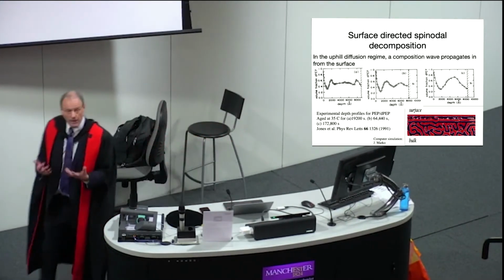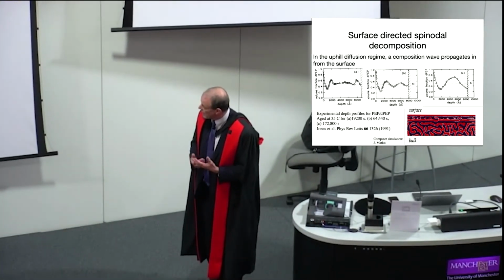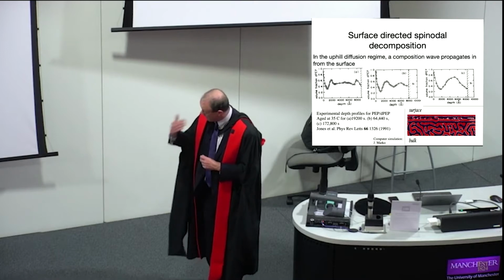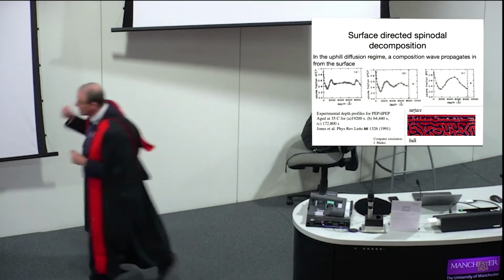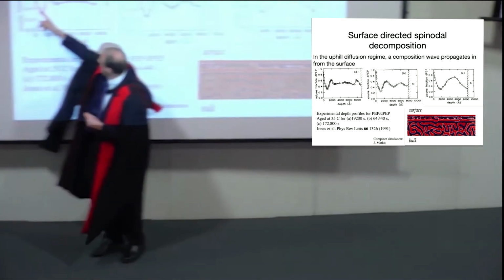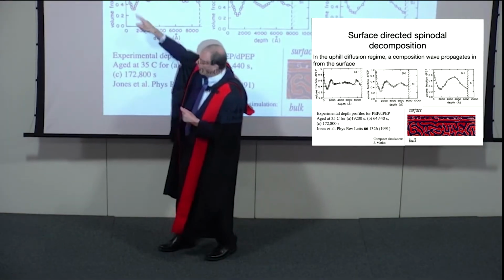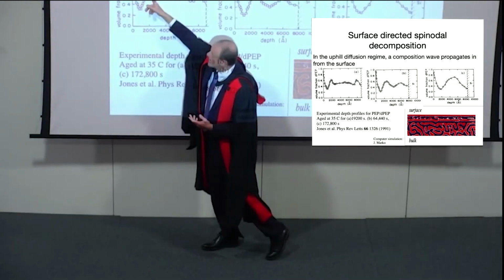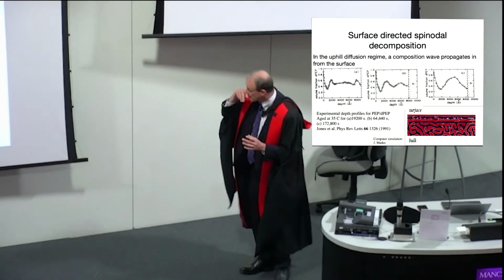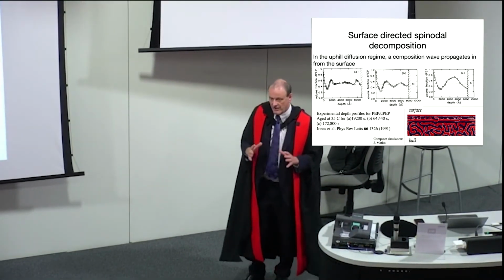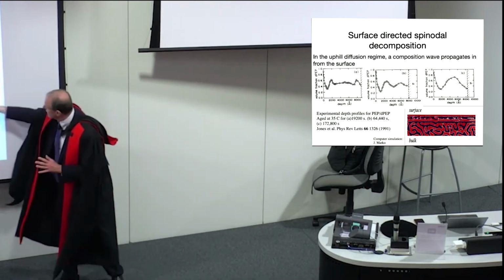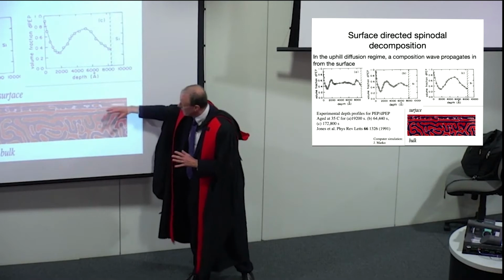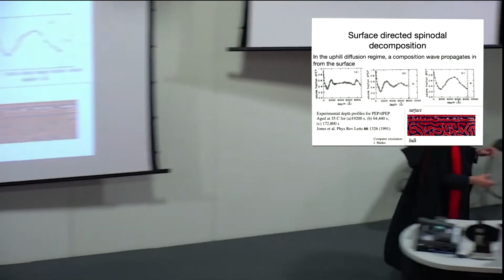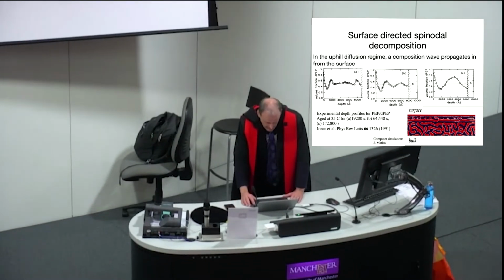And then, to go back to this idea of uphill diffusion, if you have a polymer that has one component with a lower surface energy, what happens is that the low surface energy stuff goes to the surface, it makes a hole. Now, because there's a hole and the diffusion coefficient is negative, now stuff starts diffusing out of the hole and makes the peak behind bigger. So you end up with this idea of a composition wave, if you like, growing into the surface. So this exemplifies this idea of self-stratification. This is a computer simulation, that you get this one or two layers of pure material just form by themselves. And so I'll come back to this in more complicated circumstances.